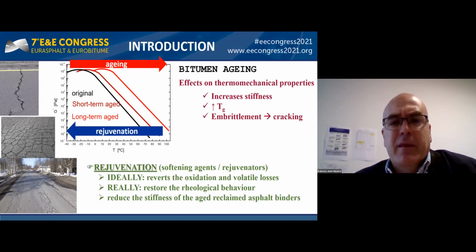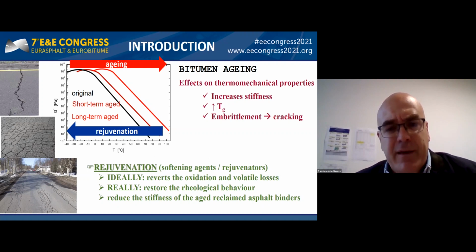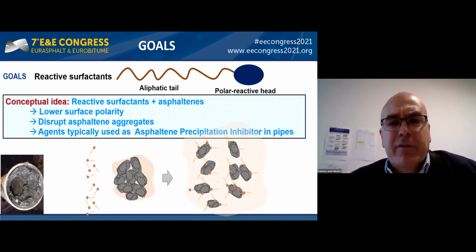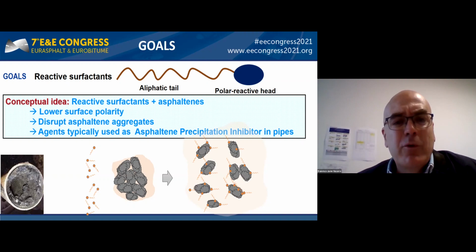According to this, even though bitumen rejuvenation ideally should revert the effects of oxidation and volatility losses, in fact, what they really do is to restore the original rheological properties of the binder, so that most of them are softening agents that reduce the stiffness of the aged bitumen. Here, a new concept of physicochemical rejuvenation is presented that involves the use of amphiphilic surfactants formed by a long aliphatic apolar hydrocarbon tail with a polar reactive head able to chemically interact with polar bitumen compounds. Therefore, it is expected that by attaching reactive molecules to asphaltenes, the surface polarity is reduced and then their association into larger structures is inhibited, leading to a disruptive effect.